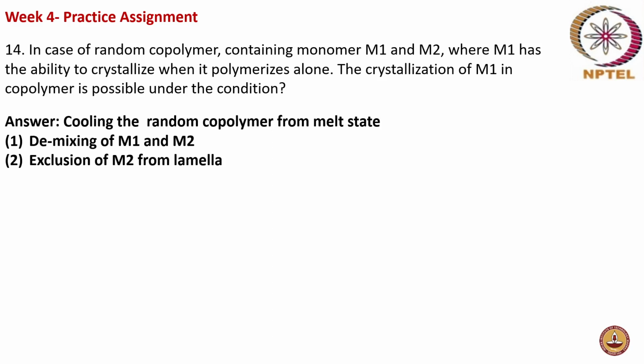So as I said, for random copolymers, if one of the monomers is able to crystallize when it polymerizes alone, in a copolymer the crystallization becomes difficult because you will have M1 and M2 randomly placed. So what you have to bring in to have crystallization of M1 in a random copolymer is that when you are cooling the random copolymer from the melt state, there should be a demixing of M1 and M2 and then exclusion of M2 from the lamella, so that in those places where M2 is excluded and M1 is there, there is a possibility that M1 starts crystallizing in that zone. This is the condition where crystallization is possible in a random copolymer.